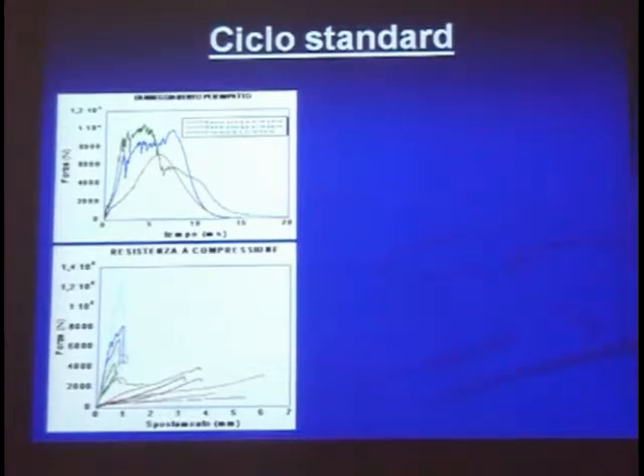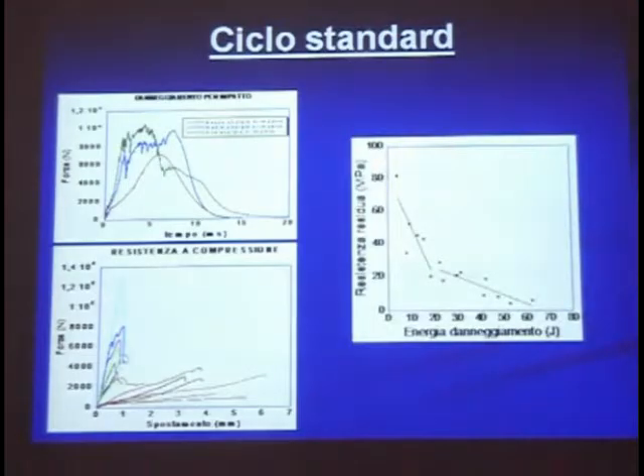First, you get a very high strength, and then the strength is reduced, and then at a certain level of damage, the behavior changes completely. And in this case, the sample is badly damaged, although not completely broken. And this results in the two-stage curve in the residual strength versus damage energy. You see, you have two stages clearly visible. For low energies, you get a slope which is higher than for high energies.